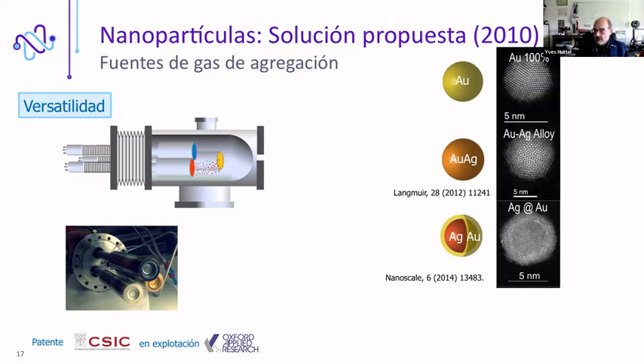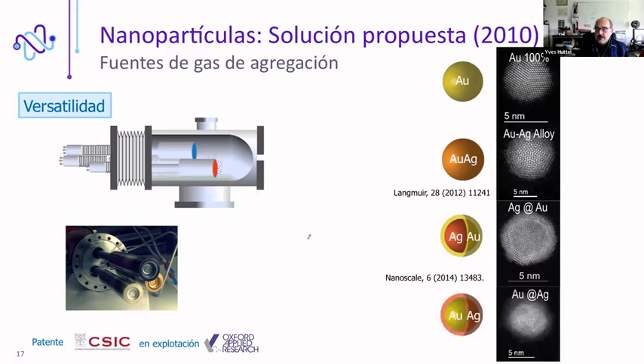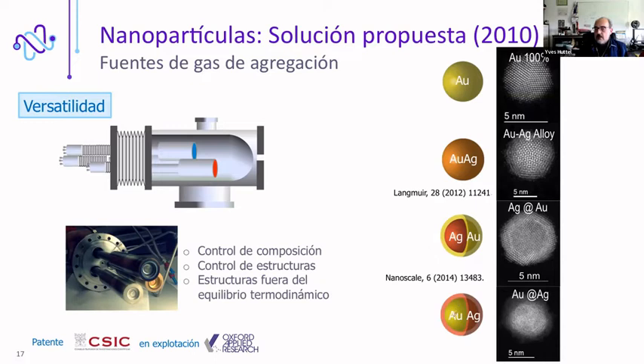Here you have the example in TEM. So you can see the gold that is heavier, that has more electrons, is brighter, and we clearly have a shell of gold surrounding the core of the silver nanoparticle. But we could also make the inverse by placing the magnetrons like this, and make a gold nanoparticle covered by a silver shell. Here, the silver shell appears not crystalline because the silver is oxidized, right?